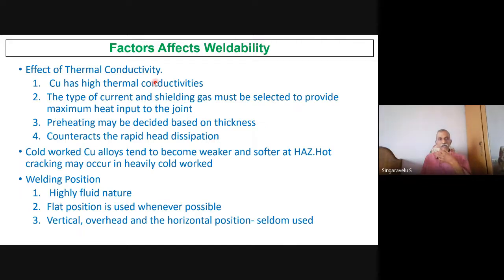So this thermal conductivity counteracts the rapid heat dissipation. Cold worked copper tends to become weaker and softer at the HAZ. Hot cracking may occur during welding. Welding position, highly fluid nature: the flat position is used because of the highly fluid nature; wherever possible you have to use the flat position. Vertical and overhead are rarely used.